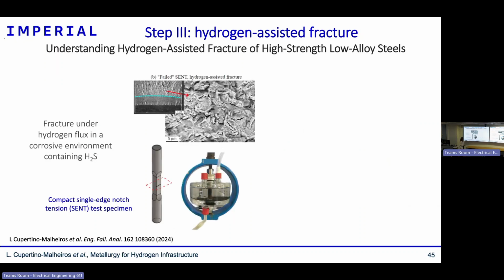All right, so here a new geometry of a compact tension test was developed. So it's a fracture test. This test was then performed in those cells, in which there is an acid environment with H2S. In those cells there is a constant load during 30 days. And basically what we get is whether it passes or does not pass.